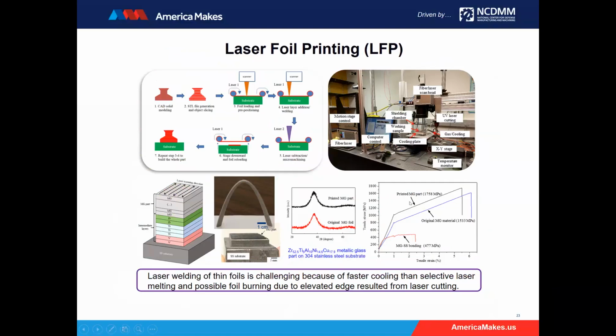And we have shown that with this process, because of the use of foil instead of powder or rod, the thermal conductivity is higher, and therefore the cooling rate is higher, and therefore the strength of the part made is higher. And because of the high cooling rate, this is good not only for making crystalline metals, but also for amorphous metals or metallic glasses. And so here we show that we are able to make parts from metallic glasses. Sometimes, because of compatibility issues, you may have to have some intermediate metals, including the metallic glass. So all these are part of research.